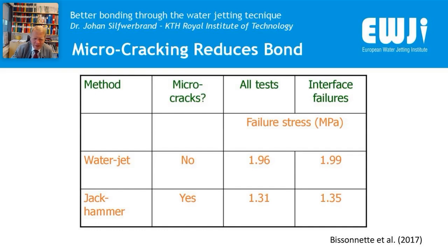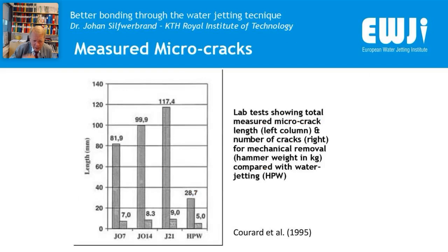Very clear difference. And another international researcher is Luc Courard from Belgium, and he developed a method to measure the microcracks. And here you can see the comparison between jackhammers with the weight of 7, 14, and 21 kilogram. And then you have the high pressure water jet. And you can see that there are some minor, small lengths of cracks also for the water jet technology, but they are much smaller.